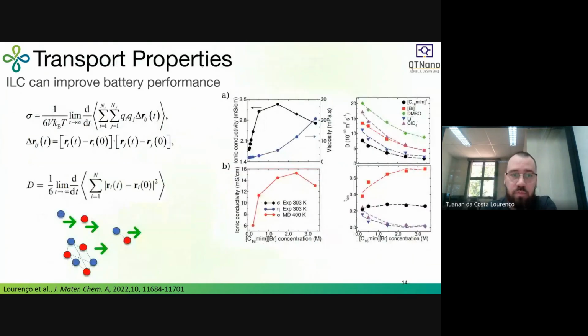of the electrolytes. So if we look here, in this first plot we have experimental data for viscosity. So blue is viscosity, and the data is here on the right side. And in black, we have the ionic conductivity, and here on the left, we have the data. So this upper part here is the experimental data. And in the x-axis, we have concentration. So we are increasing the concentration of the ionic liquid inside the organic electrolyte. When we look into the viscosity, we see basically a constant increase in the viscosity when we have more and more ionic liquid.